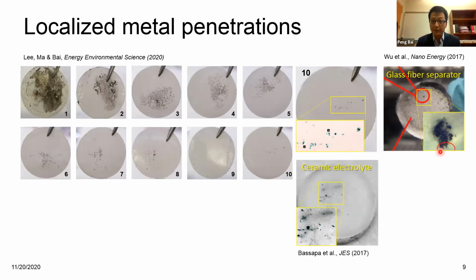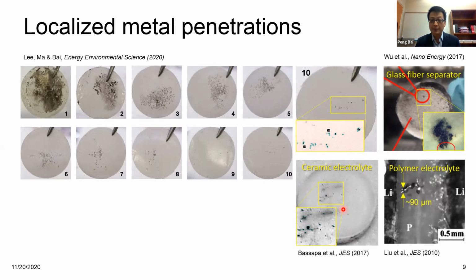And this also happened for ceramic solid electrolyte. You can see here for this very large pellet, only a few dots. You can see the penetration. And also something observed in polymer electrolyte. So everywhere, whatever kind of separator, with the liquid electrolyte or solid electrolyte pellets or films, you always see this penetration